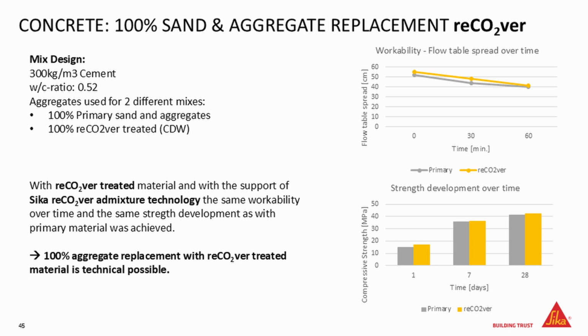So of course we said, okay, can we use the aggregates that we get out of the reCO2ver process? What we did is we had a mix design, 300 kilograms of cement, water cement ratio 0.52, and we made the same concrete using 100% primary aggregates, and the same concrete with 100% reCO2ver-treated aggregates. So we are not talking anymore about 25%, we are talking about 100% replacement. Of course, we are an admixture company, so we could adjust the admixture a little bit, but a concrete with 100% recycled concrete without the reCO2ver process is impossible. And that shows that this is possible. Using the reCO2ver, you can replace 100%.